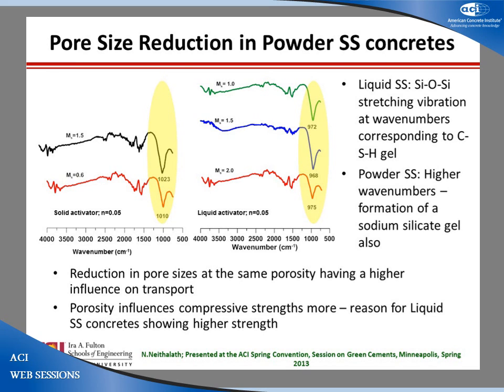Whereas if you go to the powder activated mixes, that shifts to a higher wave number, about 1023, indicating a more polymerized gel. Your CSH is not getting more polymerized. What you have is, because of the inadequate dissolution, you're forming a sodium silicate gel that intermingles with your CSH gel, which is more polymerized. That's giving you this. And the sodium silicate gel, which you can see under microscope, is a very homogeneous, non-porous gel, which makes your overall porosity much lower.